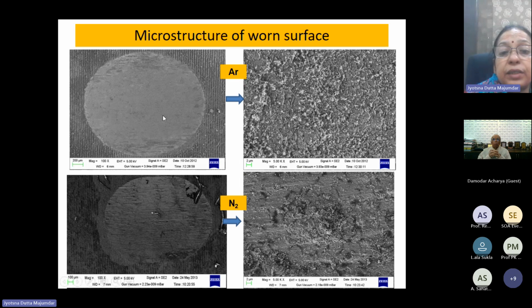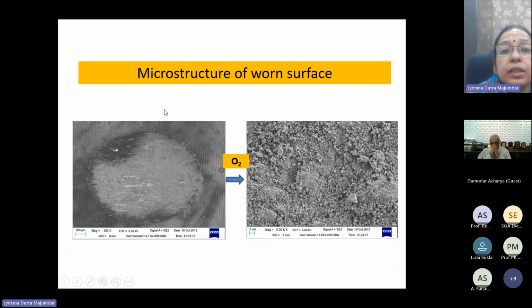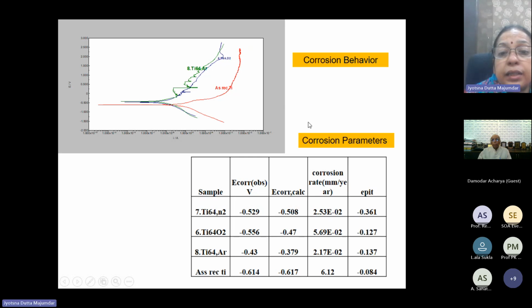So we find that in nitrogen environment the wear volume is lower than that of the argon environment textured samples. If you see the microstructure of the worn surface, you see that this is typical fretting, where the characteristics of fretting wear are observed over here. And interestingly, if we see the corrosion rate due to texturing, it was observed that corrosion rate was significantly reduced on the textured surface. It is too much reduction in the corrosion rate.